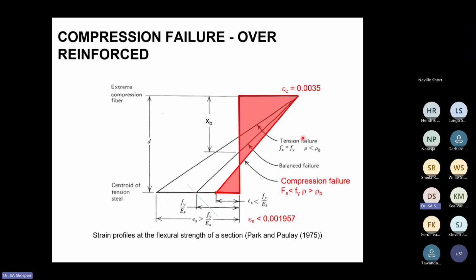An over-reinforced concrete beam would be where the steel does not yield and the concrete reaches its maximum capacity before the steel can yield. And you can see here that neutral axis is dropping right down over here, and this would be classified as a compression failure. And this failure would be a brittle type of failure, a very sudden failure. So this is a failure we don't really want in our structures. We'd rather have a lot of warning before we see the failure happening. But here, if the element is over reinforced, you would get the concrete maximum strain reached, and that maximum strain is 0.0035 before the steel reaches the strain at which it yields.